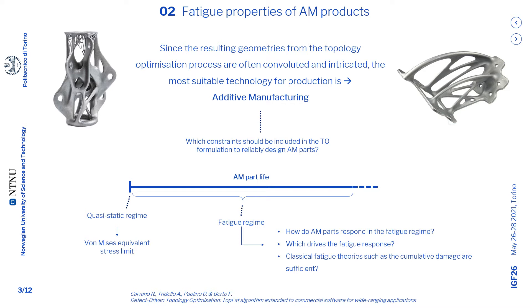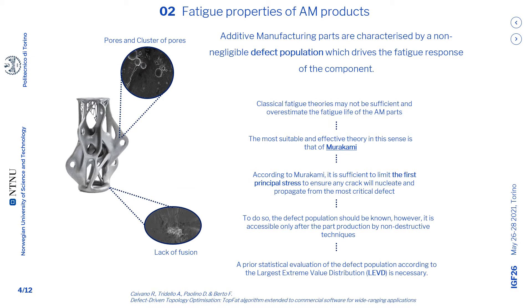Looking at the life of the components, if the quasi-static regime is considered, a constraint on the von Mises stress may be sufficient. Instead, if the fatigue regime is considered, several questions must be answered to understand which constraints and fatigue model must be included — for example, how AM parts respond in the fatigue regime, or what drives the fatigue response. The most important aspect to consider is the defect population, which affects the AM product's fatigue response. Indeed, AM parts are characterized by a non-negligible presence of process-induced defects, such as pores, cluster of pores, and lack of fusion. These defects cannot be eliminated, even if a perfect process parameter setup is employed. In this condition, classical fatigue theories may not be sufficient to predict the fatigue limit and may overestimate the real fatigue response of the part.